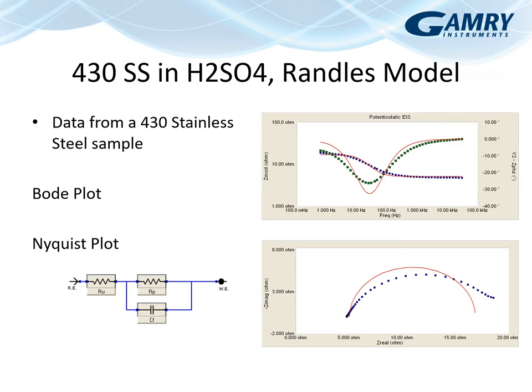To get the best values from EIS, we need to look carefully at capacitance. This data shows 430 stainless steel in sulfuric acid, with experimental data overlaid on a modeled simplified Randles circuit. The simplified Randles circuit has uncompensated resistance, a polarization resistance in parallel with a double-layer capacitance. Adding diffusion control — Warburg — gives the full Randles circuit. The best fit for this model doesn't look great: the model produces a narrower, more ideal semicircle, while the actual data is flattened and broadened.